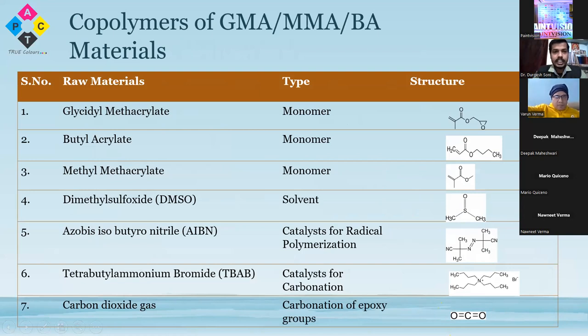So this was my first trial in which I took glycidyl methacrylate, butyl acrylate and methyl methacrylate, these three monomers, which I used in the presence of dimethyl sulfoxide, which was used as a solvent. AIBN was used as a free radical initiator, which was helpful for the radical polymerization. And this catalyst, tetrabutyl ammonium bromide, is the catalyst which is used for converting the epoxy groups into the cyclic carbonate groups. And the last raw material is CO2, which was used from a CO2 cylinder, filled in a balloon and attached to the reaction flask. So these are the basic raw materials which were used in the first trial.